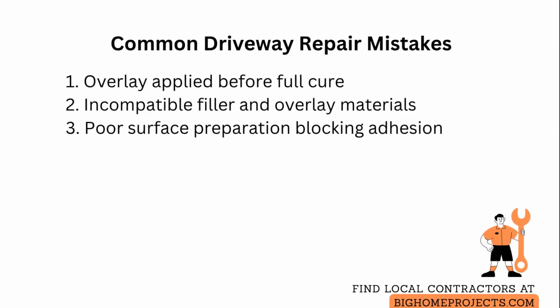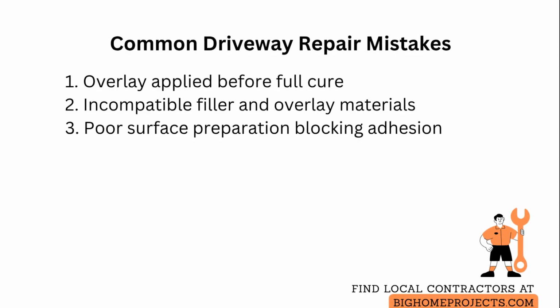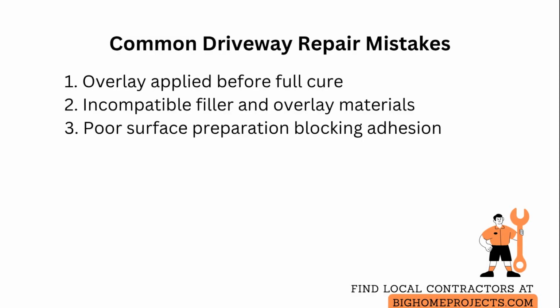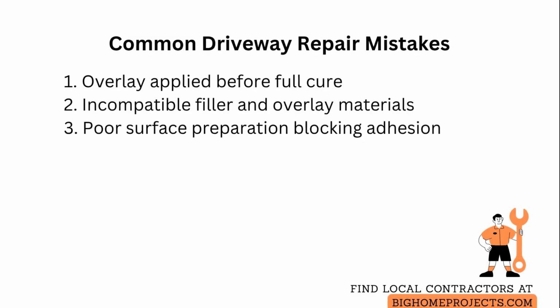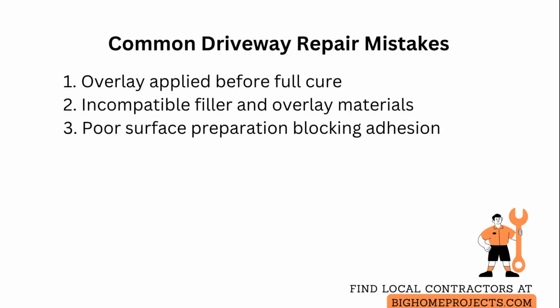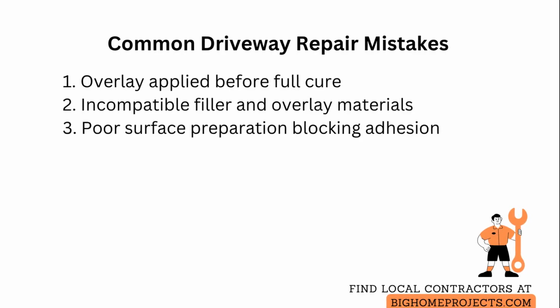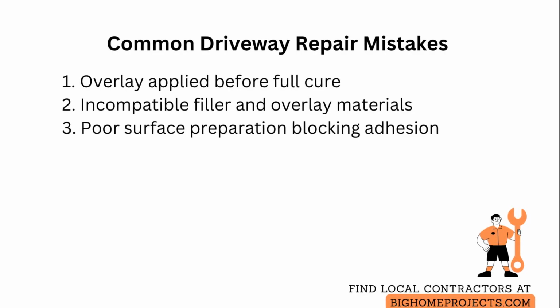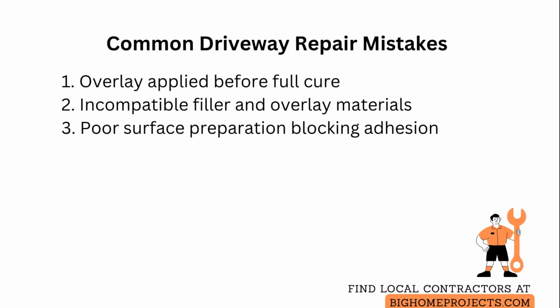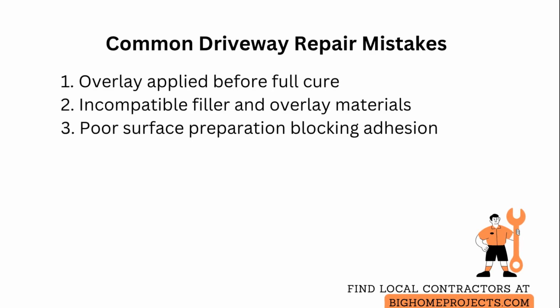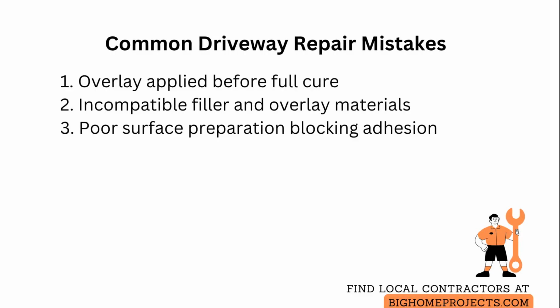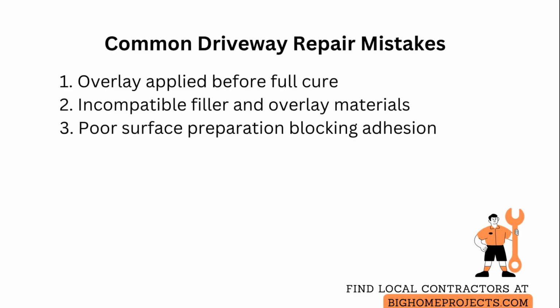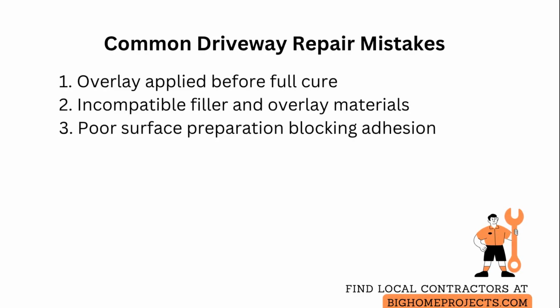Another frequent issue is using incompatible materials like a rigid filler under a flexible overlay, which causes new cracks to form. So match flexibility and test a small area first. A third concern is poor surface preparation, where dirt, oils, or efflorescence prevent bonding, and the fix is to perform mechanical cleaning, degreasing, and allow full surface drying before repair and resurfacing.